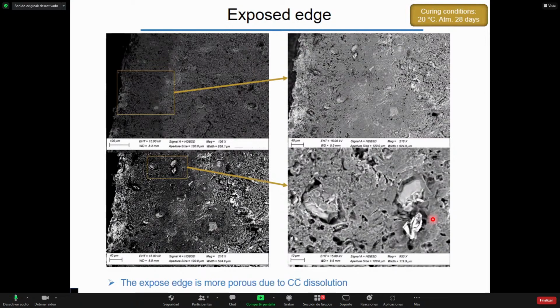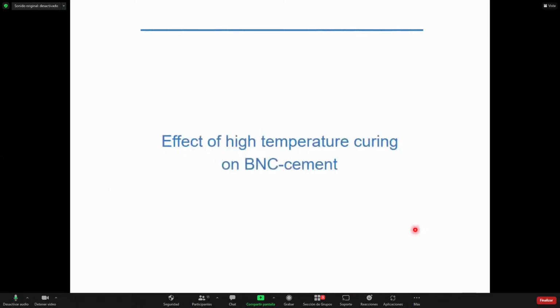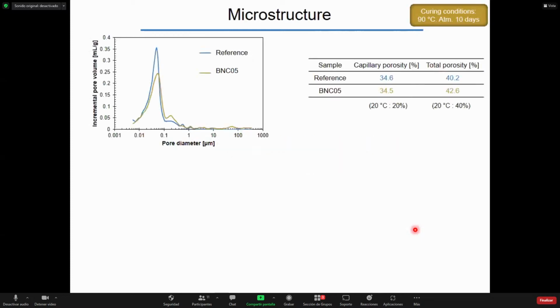Now that we have characterized this carbonated material, we will see if there is an effect of bacterial nanocellulose when we cure this material at high temperature. In the same manner, we did the same characterization as before, and in this case, on the microstructure, we saw that capillary porosity was different, but total porosity was maintained around 40% because the water to cement ratio was maintained at 0.44.